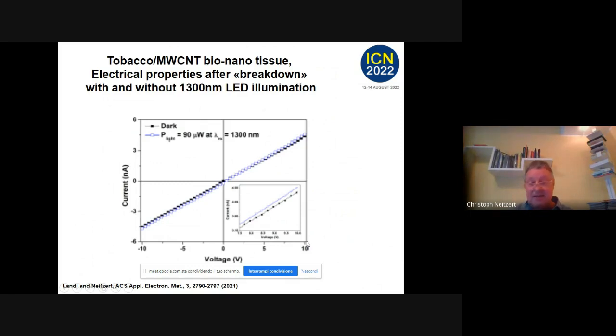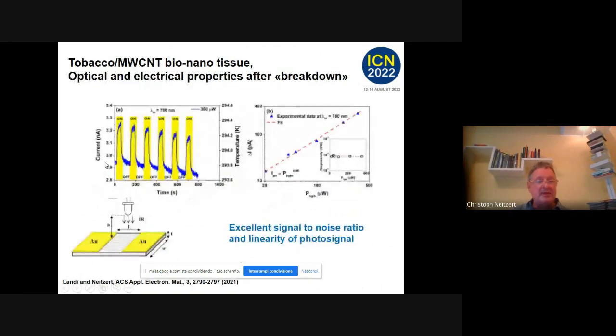This is an interesting application. We illuminate it with 90 microwatt at 1300 nanometer light, and you see the very slight change of the impedance. We can see it here. So we have a light-dependent resistor. If we have a light-dependent resistor, we have a bolometer, and what you see here is 780 nanometer bolometer operation.